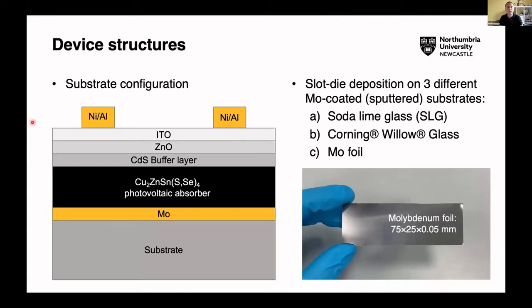I mentioned our device configuration. So we have our substrate. We coat that using sputtering with molybdenum. Then we do the process that I've just described via nanoparticle inks via slot die, and then annealing them in a selenium-rich atmosphere, or selenizing, before depositing the cadmium sulfide using chemical bath deposition in the usual way for the buffer layer, and then finally sputtering zinc oxide, ITO, and evaporation of metals on top.